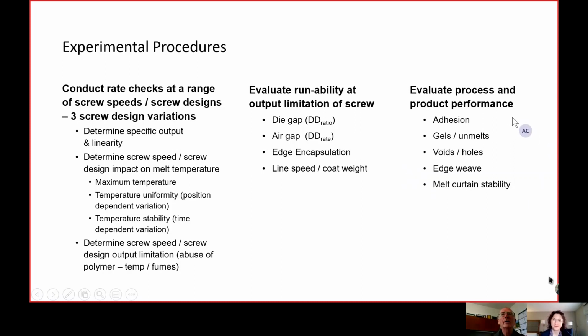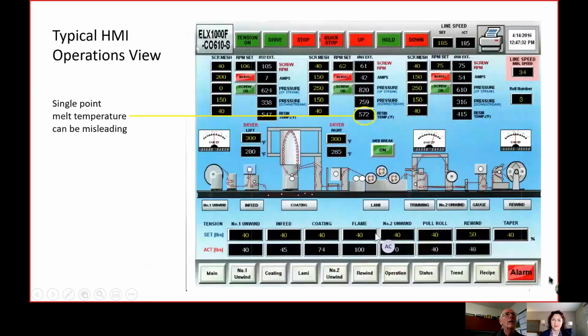The other thing we looked at in our experiment was the adhesion to the paper, and we observed the gels and unmelts in the curtain, making sure we're getting good quality melt without holes or voids. And then we subjectively looked at the edge weave and the curtain stability to make sure we're making a good product during this trial.